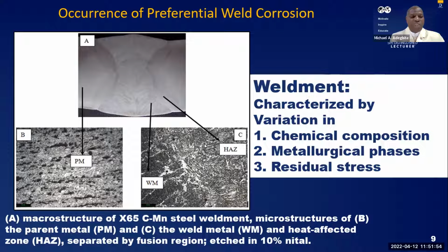And when such solidifies, we see that the parent metal retains its structure, its phase, morphology, whereas the heat affected zone has the same composition as the parent metal, but because of the intensity of the heat experienced in that region, there is crystallization, there are phase changes depending on the nature of our component. There are changes in phases compared with that of the parent metal, and these will also be associated with energy level. Of course, there is the high distortion associated with the weld metal, the metal that solidified, a highly distorted nature, we can also see.